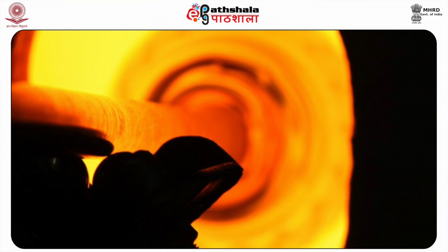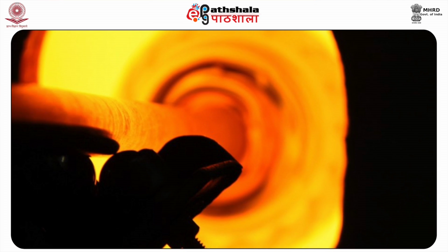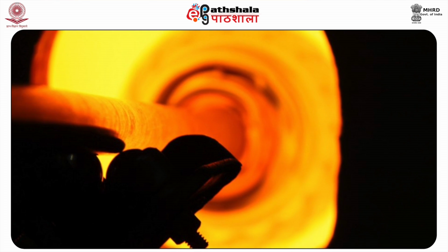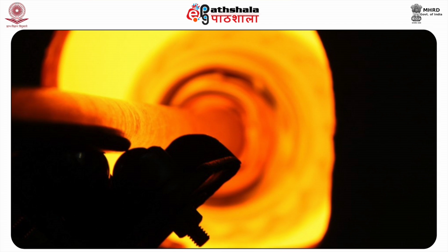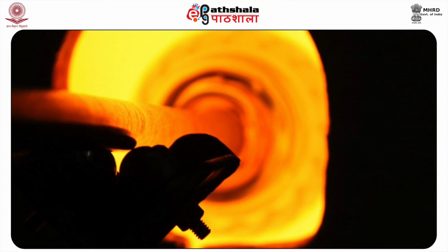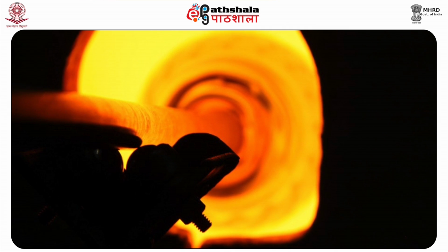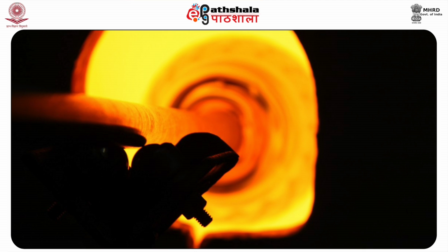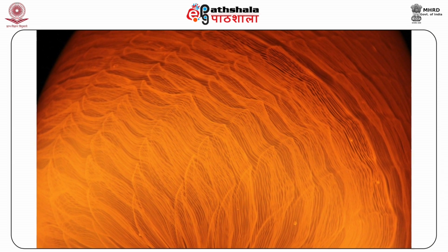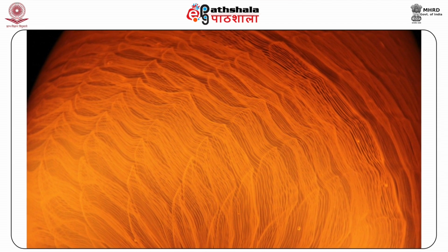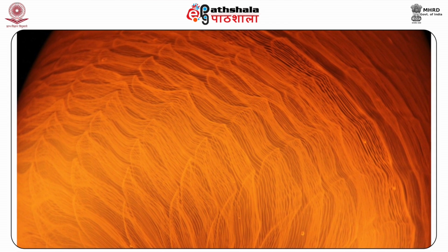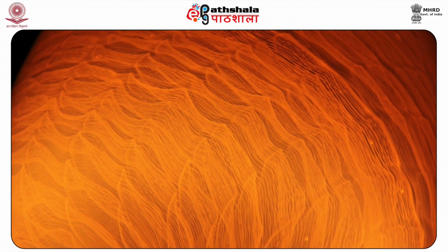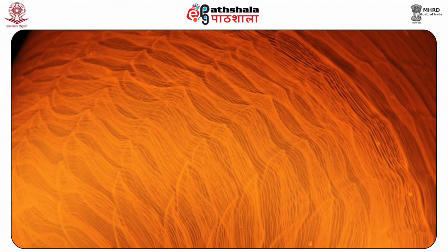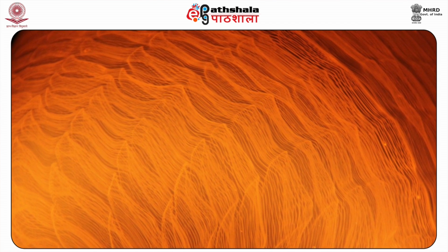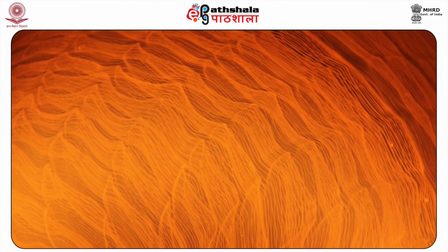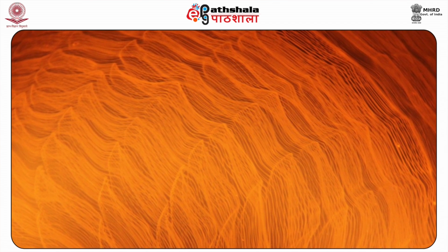Modern glass blowing technique. The transformation of raw materials into glass takes place around 2400 degrees Fahrenheit, that is 1320 degrees Celsius. The glass emits enough heat to appear almost white hot. The glass is then left to fine out, allowing the bubbles to rise out of the mass. And then the working temperature is reduced in the furnace to around 2000 degrees Fahrenheit, that is 1090 degrees Celsius. At this stage, the glass appears to be a bright orange color.